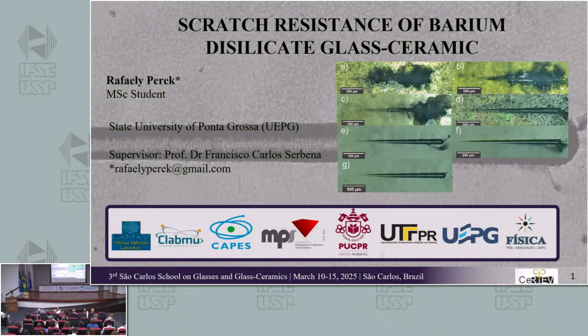The objective of this study is to evaluate the scratch resistance of barium disilicate glass-ceramic where the crystalline fraction varies from 0 to 70%, with a constant crystal size of 10 micrometers. Three regimes were identified: microductile, microcrack, and microabrasive. In the microductile regime, they increased with crystallization, while in the microabrasive regime, they decreased. The study provides guidelines for optimizing the materials design and application of this glass ceramic.